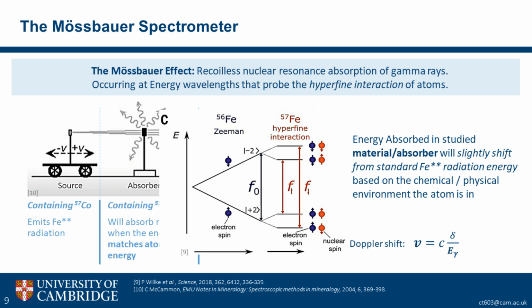The gamma rays that are not absorbed are transmitted through and collected by a detector, and we collect a sort of transmission spectrum here. The key importance is that the energy that the iron 57 isotopes absorb when they're sitting inside the sample is slightly shifted from the Fe star star radiation. And this slight shift in energy depends on the chemical and physical environment that they see. What Mossbauer discovered was that by moving the source left and right, you could use the Doppler shift and change the energy of the gamma rays that the iron 57 isotopes see inside the sample. And therefore, you can probe all the energy shifts that you're interested in when looking at the different chemical and physical environments.